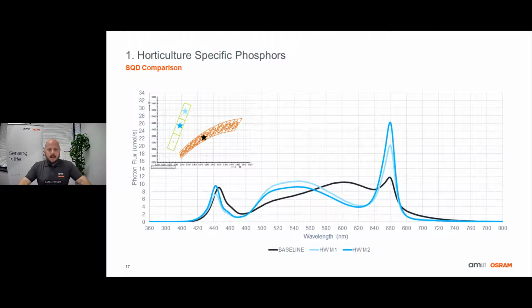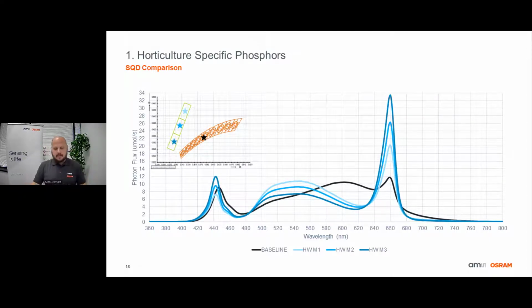Here we see how the M2 bin, which is just a little bit more blue, would look. We now have a higher blue peak and a slightly lower green hump. This enabled us to increase the contribution from direct red, and we still maintained a red to blue ratio of 2.5 to 1. And finally, we see the M3 bin solution, and just like how the M2 bin looked versus M1, we again have an increase in our blue peak, a decrease in our green, and again, we were able to increase the amount of red coming from direct emitting red.